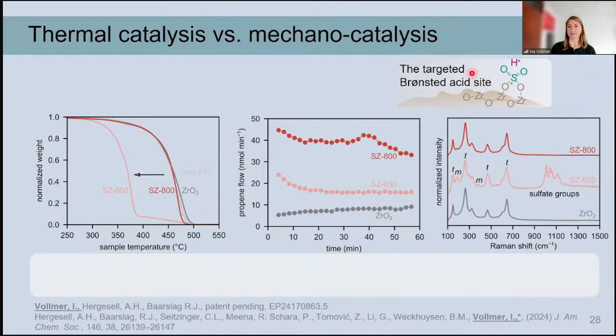And because this active site, this Brønsted active site, is related to the sulfate groups, we also measured the amount of sulfate groups on these grinding spheres with Raman spectroscopy. And there you can also see that, as we would expect, the good thermocatalyst, the one treated at 650 degrees, shows a high amount of sulfate groups, while the one that is thermocatalytically inactive shows no sulfate groups. So we would also expect that there's little Brønsted acidity on that catalyst. So there seems to be something else that we are forming that actually causes the mechanocatalysis.